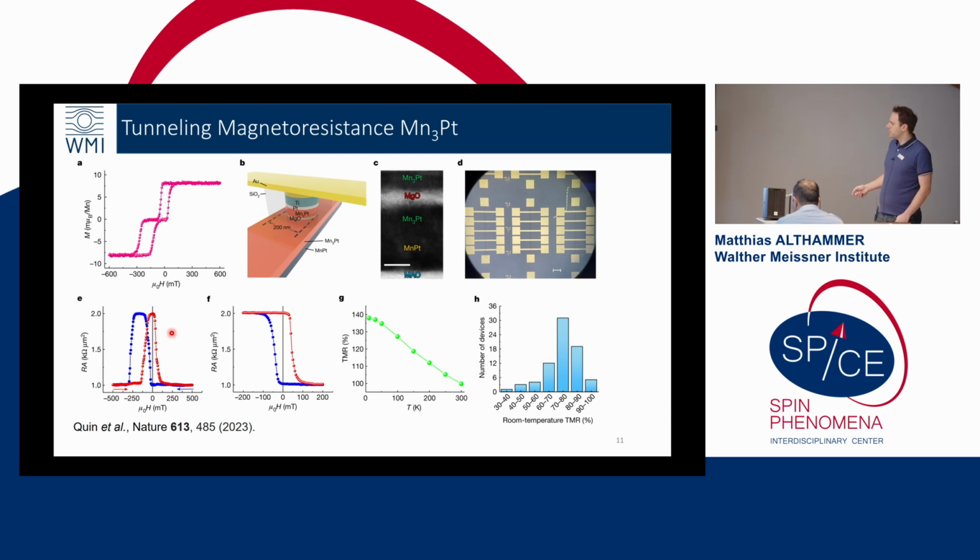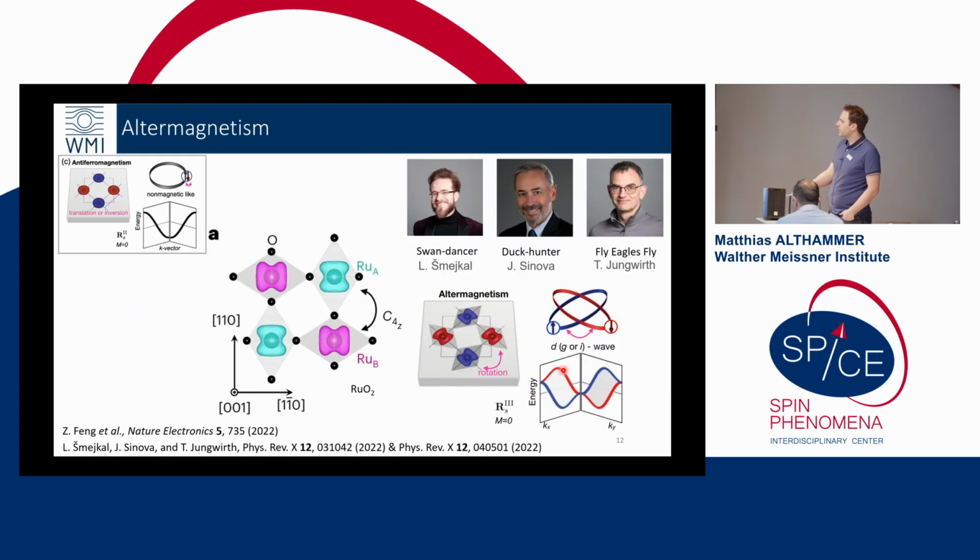And they were honest that they fabricated a lot of different devices, but still you see that you get finite tunneling magnetoresistance values at room temperature with these structures, and can now also think about some applications, because the size is already quite large. Now questions would arise how you can switch that system faster to go for memory applications, maybe in the future.